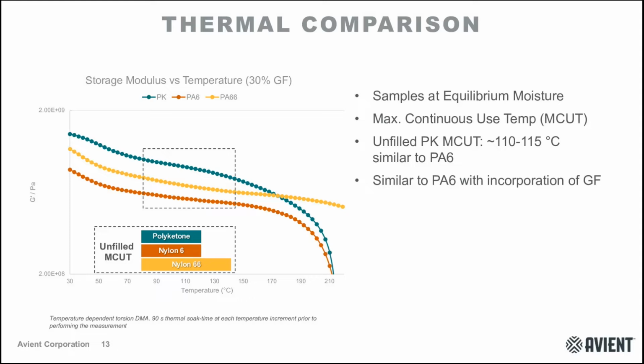So what this tells us is probably a good rule of thumb is that polyketone max continuous use temperature is probably more likely similar to a nylon 6 than a 6,6, especially when we are reinforcing the material with glass fiber. If we're talking about unreinforced resin, the max continuous use temperature of polyketone is probably somewhere around 105 to 110, although there are certain things we can do with different additive and stabilizer packages to move that up a little bit, similar to that of nylons.